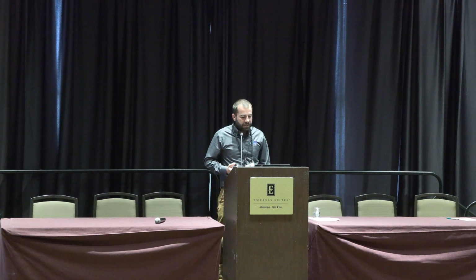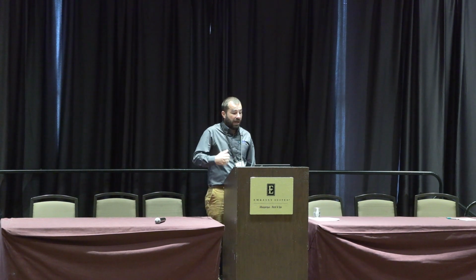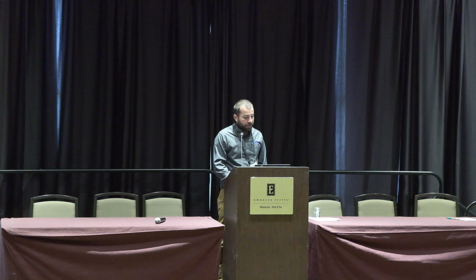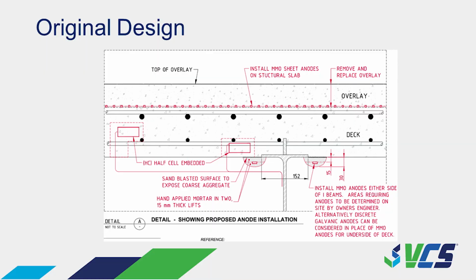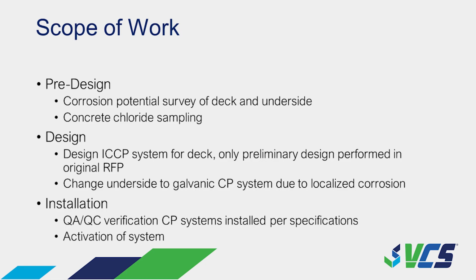So we said, is this really the best way to protect the top of those beams in that area? We started with pre-design work where we went out and really looked at the structure, did a corrosion potential survey and concrete sampling to understand the risk for corrosion in this deck. Then we worked with the contractor and design-build team on a design where we took the original ICCP for the top deck, but changed the underside to a galvanic system, which would be more effective in a targeted situation. My group and my team performed quality control and quality inspection for the CP system installation to make sure it went in properly per the spec, and then activated the system.